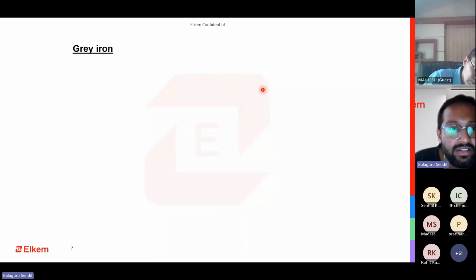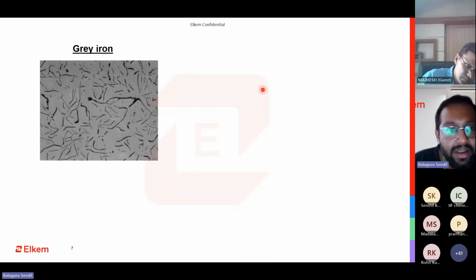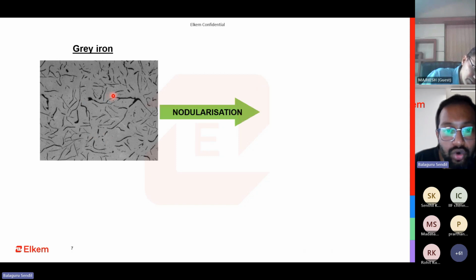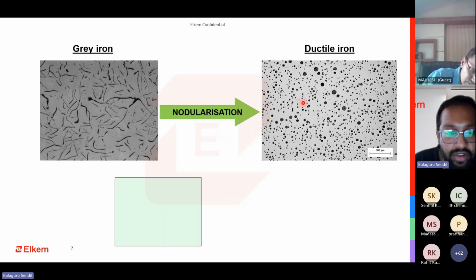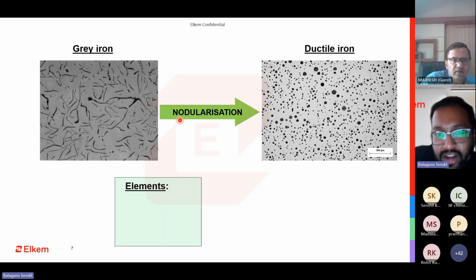What we have seen here is that gray iron typically looks like this. We know that this is a very good gray iron microstructure. And when you do nodularization, you get a ductile iron microstructure like this. So what is nodularization? You have to use elements which can actually help in changing the speed. In the second slide, we discussed that the growth rate between the basal and prismatic plane has to have a certain equilibrium. If that equilibrium gets distorted, then you will not get the correct amount of nodules. You will get flakes in between, you will get CGI, all these things.